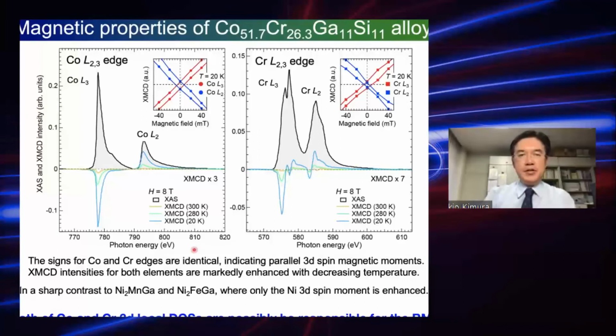So here you see the X-ray magnetic circular dichroism spectra at cobalt and chromium edges for the cobalt-rich sample. As you can see, at both elements, cobalt and chromium edges, you see the same sign, identical signs. And again, this indicates a parallel magnetic moment between the cobalt 3D and chromium 3D spin magnetic moments.